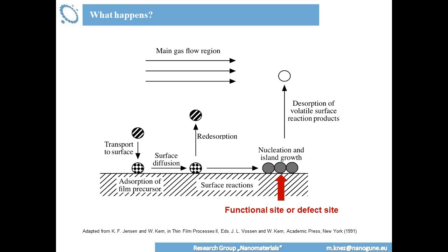That means you don't care about this surface anymore. Your ALD growth will happen here. And it will happen here by being fed either from the gas phase with the precursors or through the substrate. That means you need to really also consider this possibility that the precursor will attach to the substrate and will diffuse to the next nucleation point, bind to your spot and start growing the new cell.